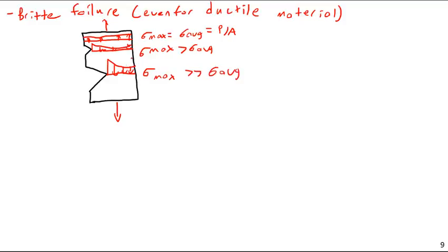So what tends to happen is this is an example of compounding failure. You get a little crack that causes a slight increase in the stress at this location. That causes the crack to open up a bit. And then once that happens, the stress becomes even more concentrated, which means the crack opens up even more. So this is actually how paper clips fail. They start with little microscopic defects, and by bending it back and forth, you increase the stress, you increase the defect, the cracks expand, and the whole thing fails.